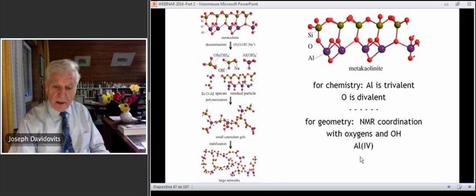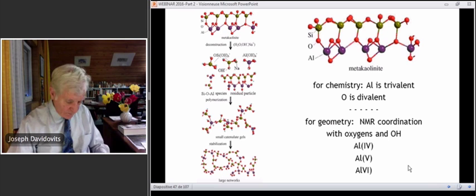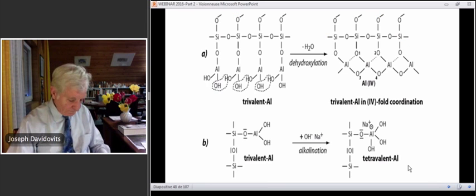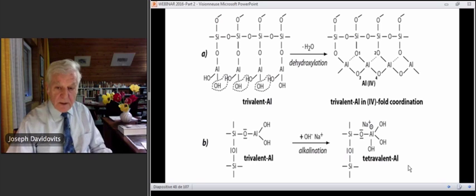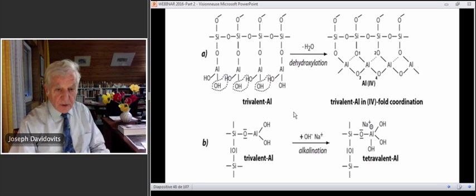But for metakaolin we have Al4, Al5, and also Al6. So how do we represent this? This is not here. So we have here confusion between covalent bonds and the geometrical relation of one atom with the surrounding atoms. So if we see it differently, we have trivalent aluminum.